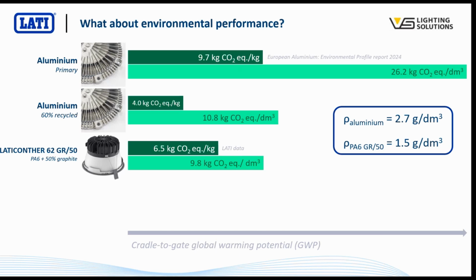And the even cooler thing than all of that is that we now have a new version of this material as well. So in this grade here, all of the nylon 6 is virgin nylon 6. We have a new version where we replace all of that virgin nylon 6 with nylon 6 that's chemically recycled. So this is material that's made from a mixture of post-industrial and post-consumer waste. So it might be nylon carpets, it might be nylon fishing nets, it might be various bits of clothing. All that is broken down back to the monomer and repolymerized to give a 100% chemically recycled nylon 6.